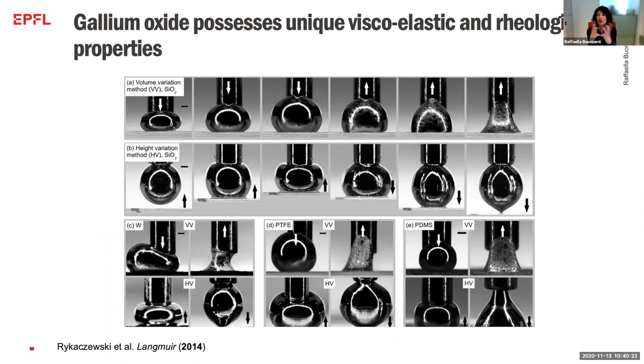So why do we get this shape? Well, what I'm showing you is what happens to a liquid gallium drop that sticks on a surface. It turns out that this gallium oxide has really special viscoelastic and rheological properties. So basically it really sticks to metallic surfaces. It's kind of similar to what happens at our interface between the copper and gallium. So this was quite interesting for us.